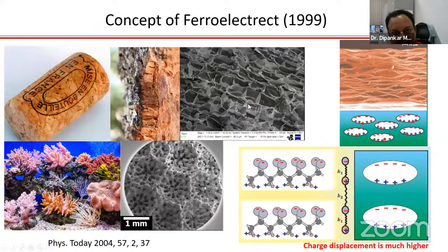This part I'm not discussing, but it is very interesting to know, just as take-home information, that PVDF or polymers have a very limited piezoelectric coefficient, like 35 picocoulomb per Newton. But if one wants to increase it, one way is to make cellular structures like coral and some wood have. So you have to artificially make some sort of cellular structure, meaning pores. What happens then? If we discharge it at high voltage, these pores get ionized, positive and negative charge separation. So these act as a macroscopic type. So once you have a PVDF, this is the macroscopic dipole and this is the microscopic type.